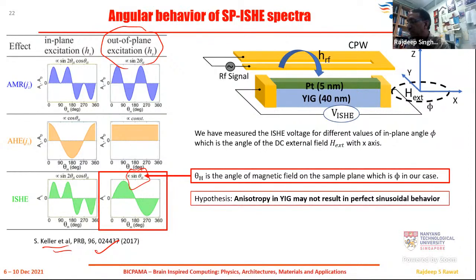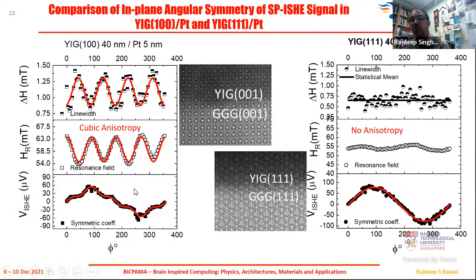So for any materials, this is basically modeling based results, and that is what is predicted. But our hypothesis is that in our case, because we are investigating YIG with the different orientations being grown on that different epitaxy of the film, they have different anisotropy present over there. It's a cubic anisotropy for 0, 0, 1. It's uniaxial for 0, 1, 1, and almost like no anisotropy for 1, 1, 1. So that should affect even the spin pumping process. That means this should be modulated. So that was the hypothesis. And that is what you can see over here.